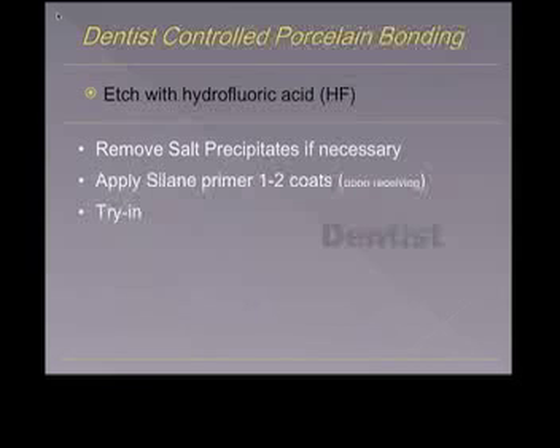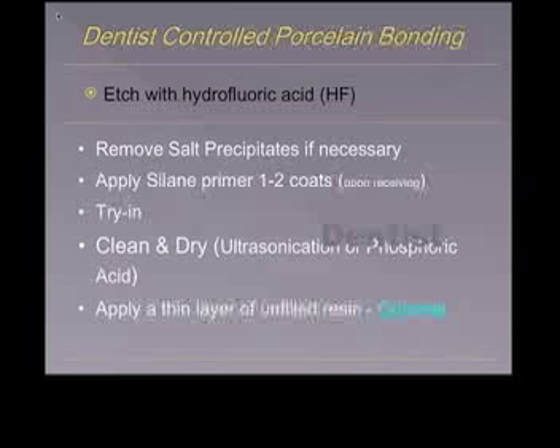So you want to etch with hydrofluoric acid, and these are the steps: remove the salt precipitates if necessary, apply the silane primer 1 to 2 coats, try it in, clean and dry. If you need to clean it, use phosphoric acid or ultrasonicate, then apply a thin layer of unfilled resin, and then your luting cement. It's a pretty easy protocol, and very easy once you get the hang of doing this.